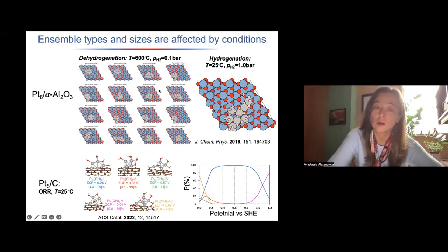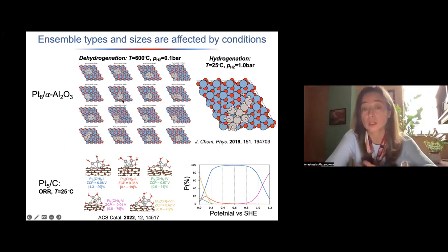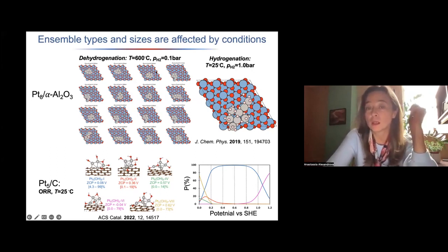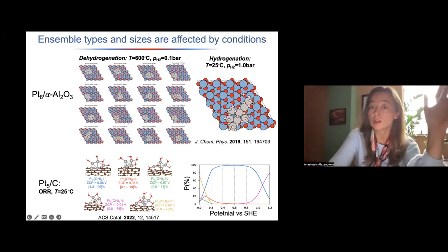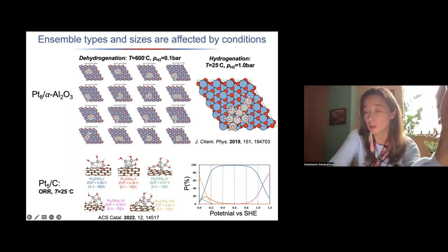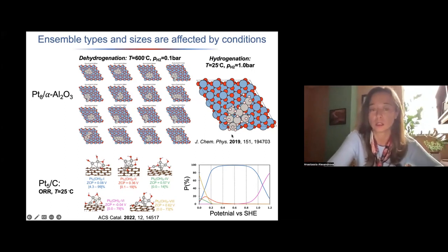So on the left, you see all sorts of isomers. Maybe it's hard to see, but they're different in structure, hydrogen coverage and hydrogen placement, as well as where they sit on the support. And all of them are there in reaction conditions. And these guys looked into just one structure, very much hydrogen covered, unusual shape, far from globular, and it's only one isomer that we can see as accessible by simple Boltzmann statistics.